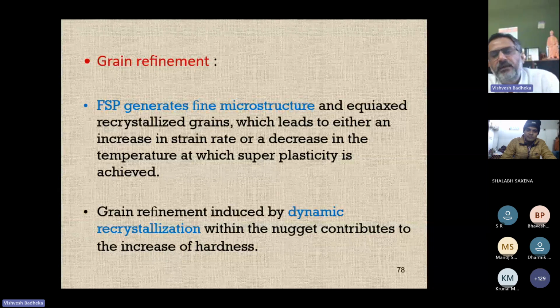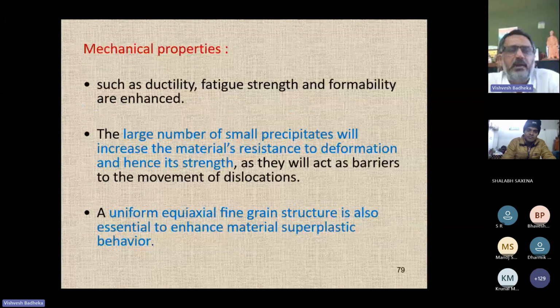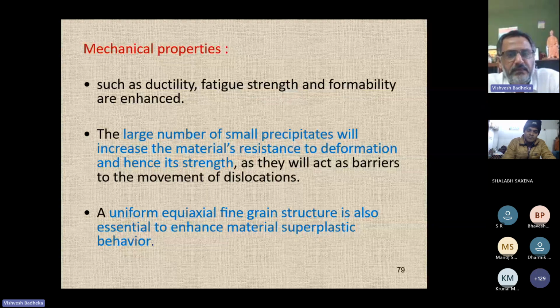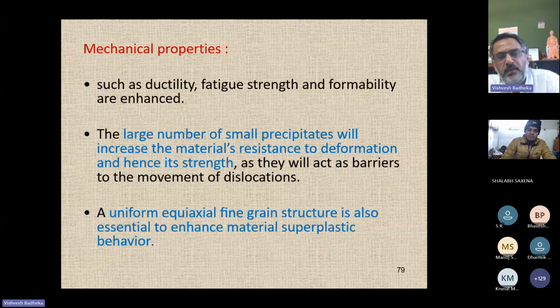The grain refinement induced by dynamic recrystallization within the nugget contributes to an increase in the hardness and other mechanical properties also. FSP also helps you to improve the formability, ductility, the fatigue resistance, right? Why does it happen? Because before FSP, you have those large precipitates.